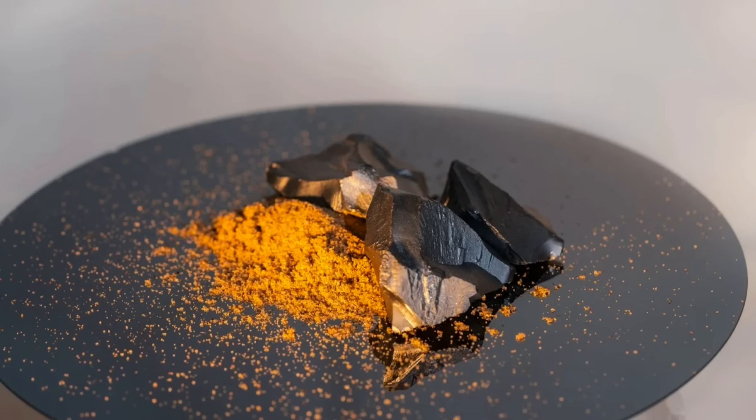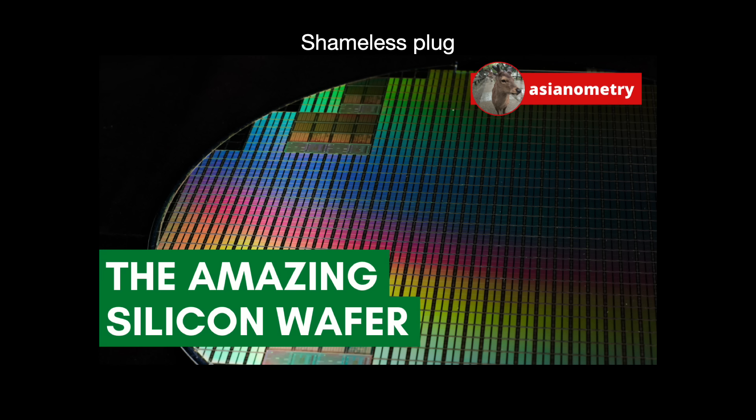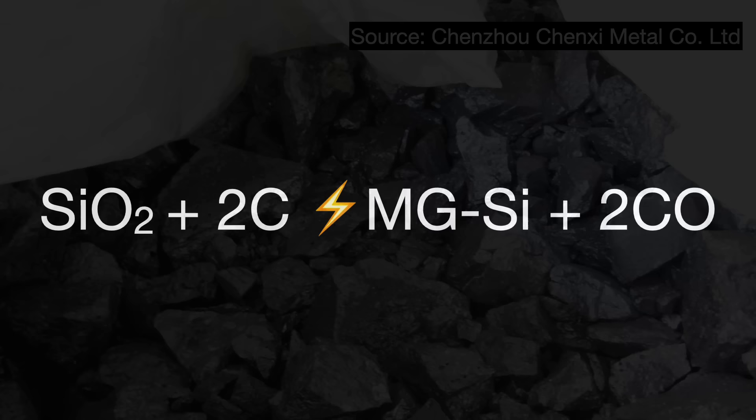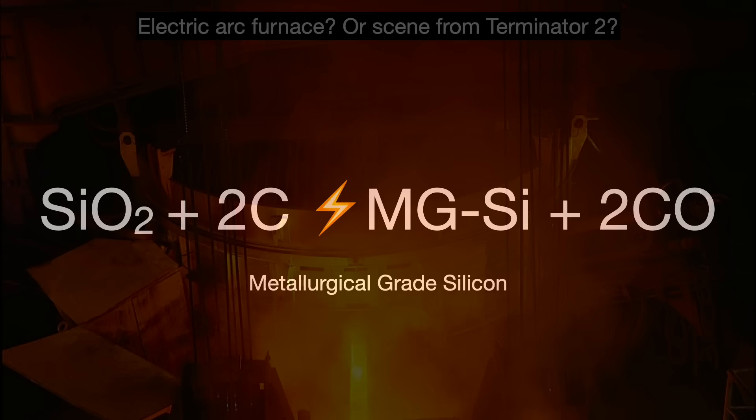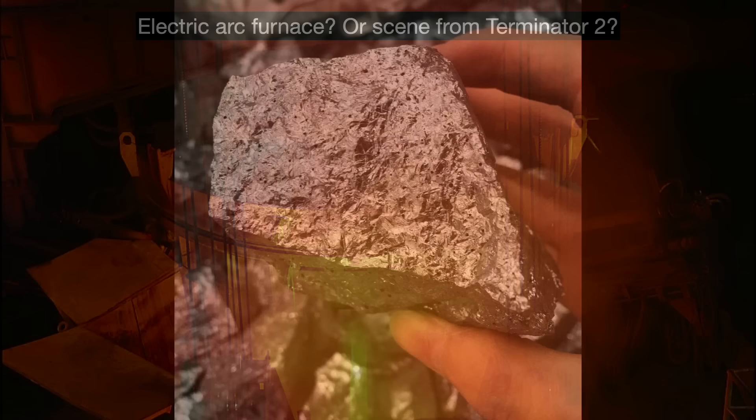This economic factor was a critical reason why the solar industry consolidated towards using silicon in the late 1970s. The reasoning at the time being that solar could sail in the wake of the booming semiconductor industry. The steps for making and processing silicon wafers for solar panels may be familiar to you if you saw my other video on semiconductor silicon wafers. We begin again with metallurgical or metal-grade silicon which is used for producing steel or cast iron. We make it by putting silica or sand together with charcoal into an electric arc furnace and heating the whole thing up to 1,900 degrees Celsius. Metal-grade silicon is 98% pure, but still contains significant impurities like iron, aluminum, and so on. This is not pure enough for solar-grade silicon, so we need additional purification.